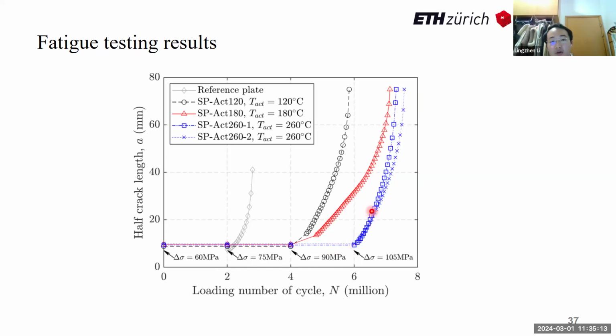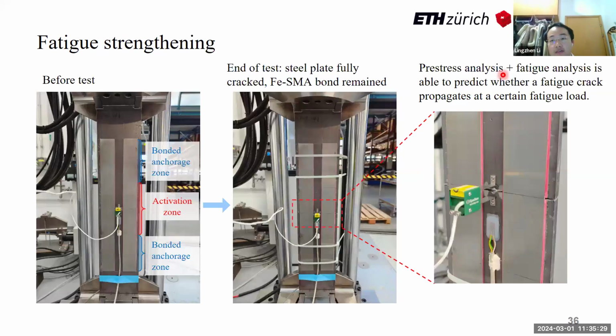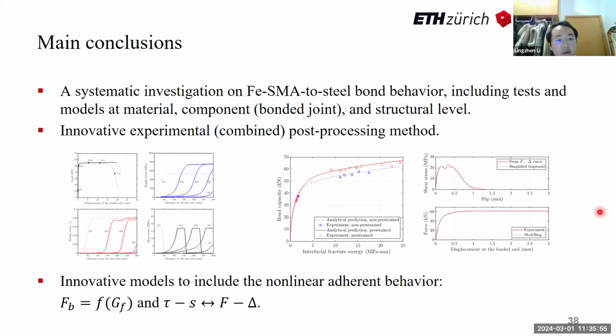Not only did the test results tell us that higher activation temperature brought a better strengthening efficacy, but also a pre-stress analysis model, which was shown in the previous slide, plus a fatigue analysis model, are able to predict whether a fatigue crack will propagate at a certain load level. These two models combined could be used for fatigue strengthening of existing structures using our bonded Fe-SMA strengthening technique. So here come the major conclusions.